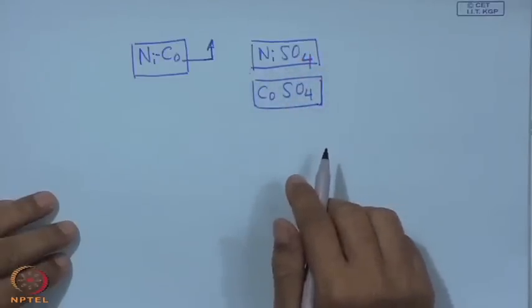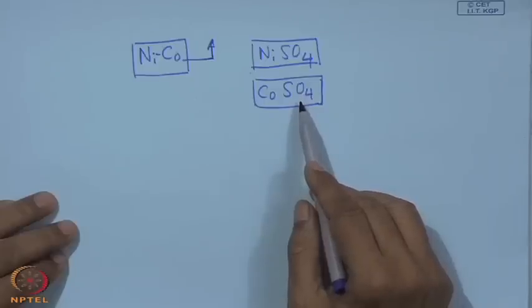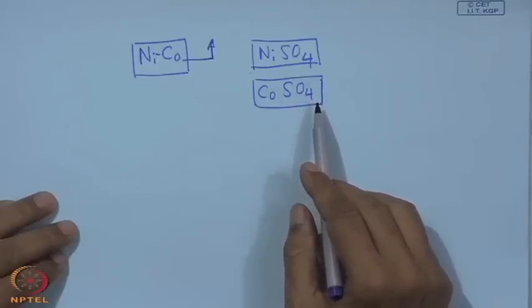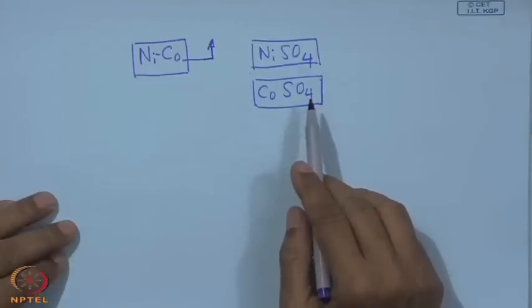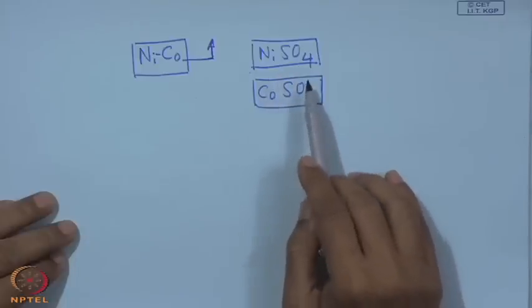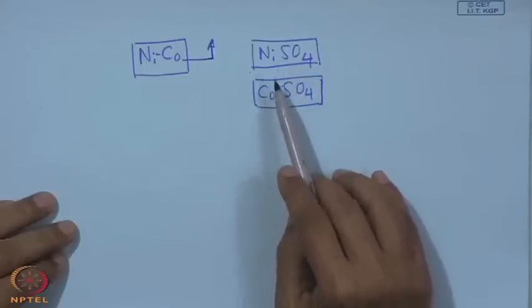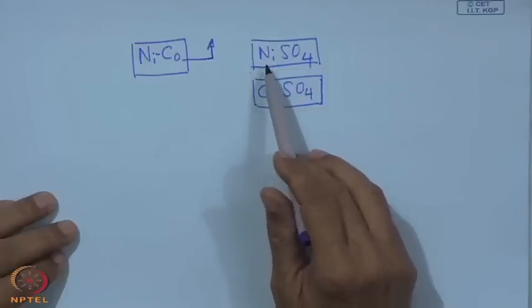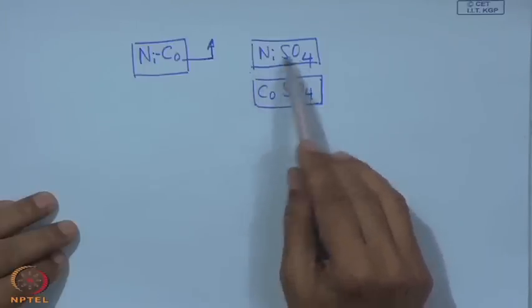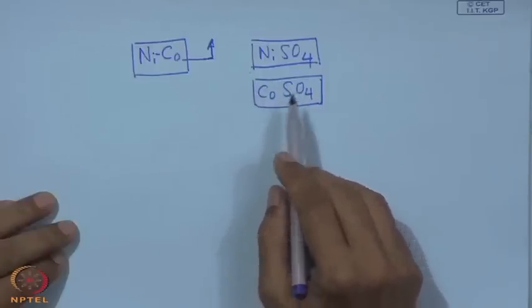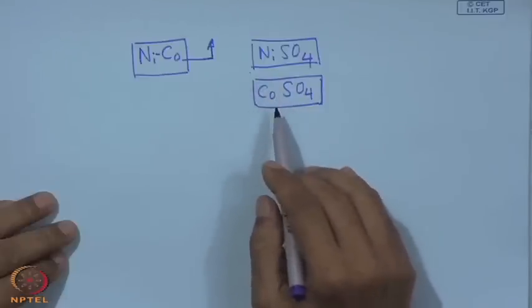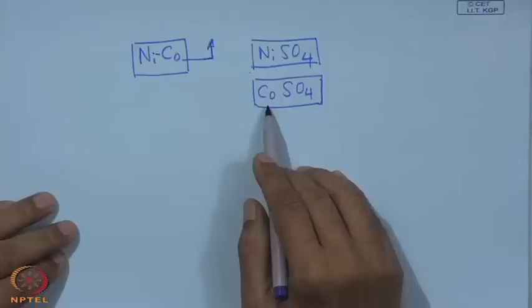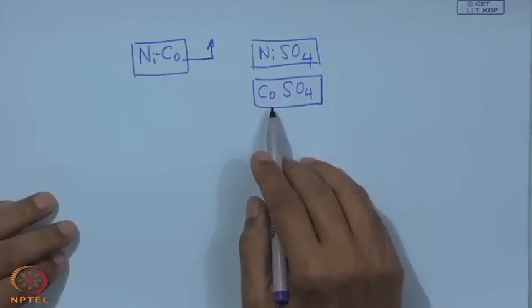So, wherever we find a combination that will be useful and when they are really compatible, then this co-electrodeposition is also possible, and in that case definitely the current density, the voltage across the electrode, and the temperature are a few things that will affect the deposition rate or the composition. So, it depends definitely on the electrochemical equivalent of nickel and cobalt and also their respective concentration, and accordingly we have the deposit with certain variation in their percentage, but in principle co-deposition by this galvanic technique is also possible.